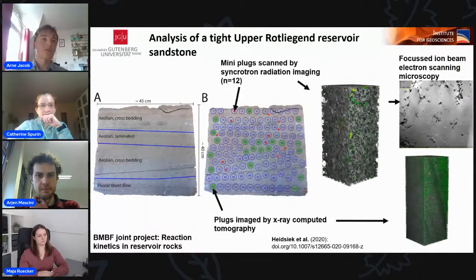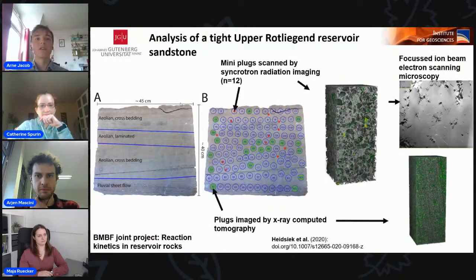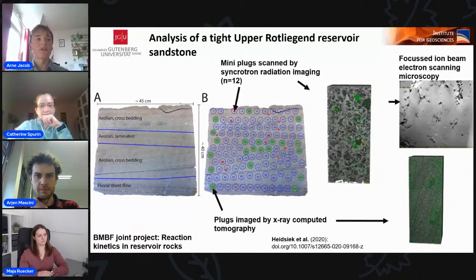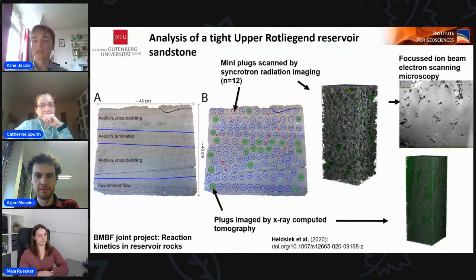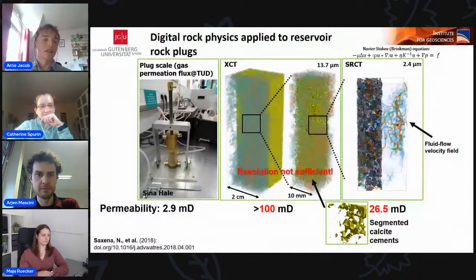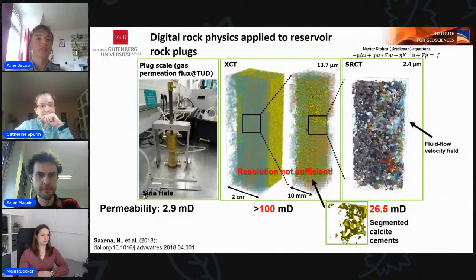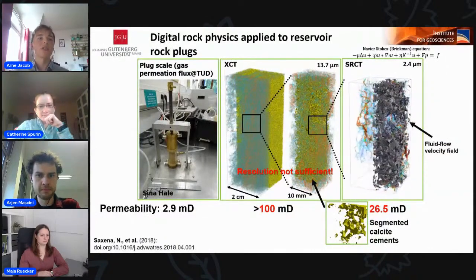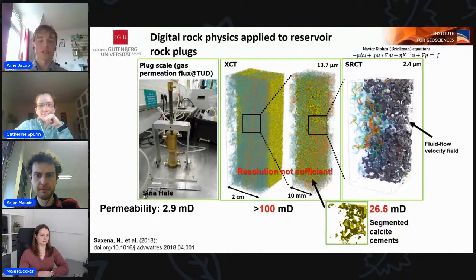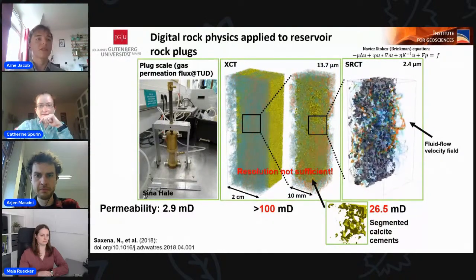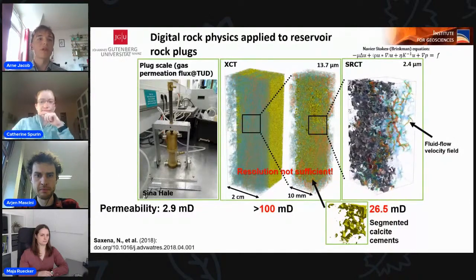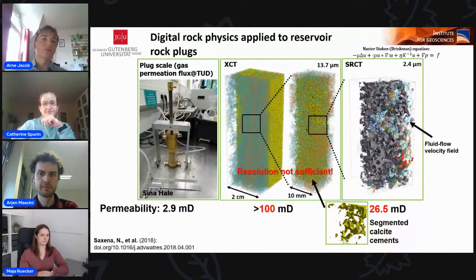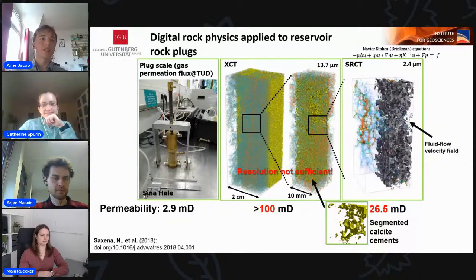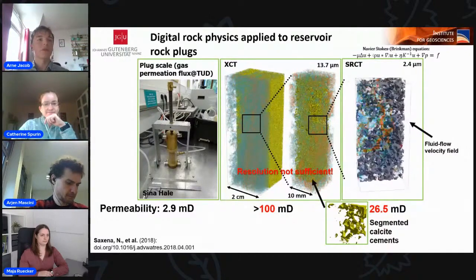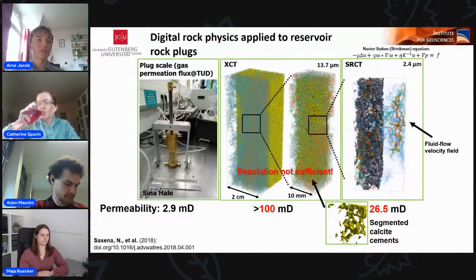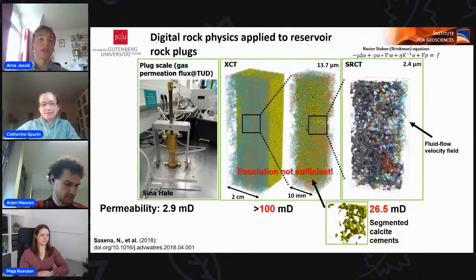For the smaller sized plugs, my colleague Markus Pelz from Greifswald conducted FIB-SEM measurements as well to resolve the qualitative and quantitative clay mineral content of the samples. So we conducted permeability measurements by using gas permeation flux experiments to determine the permeability of the larger plug samples. The intrinsic sample permeability was derived from the apparent gas permeability determined for each pressure step using Darcy's law. Since the fitting of the straight line to determine the true permeability values was very accurate, we assumed the experiment to render the permeability very well.